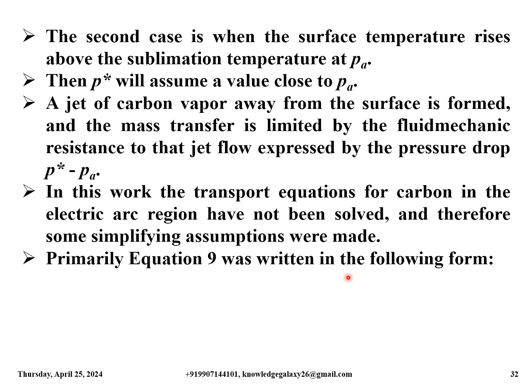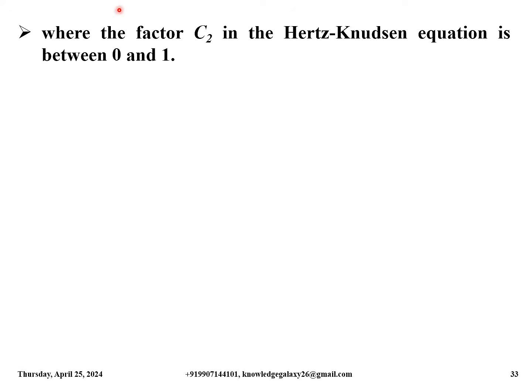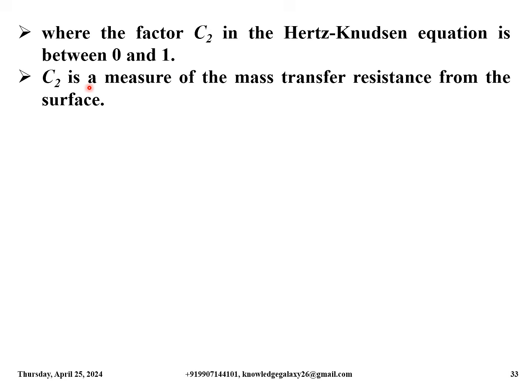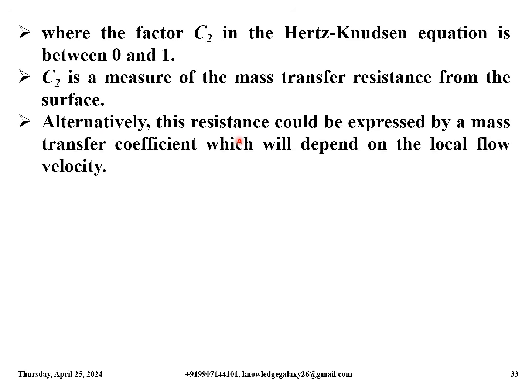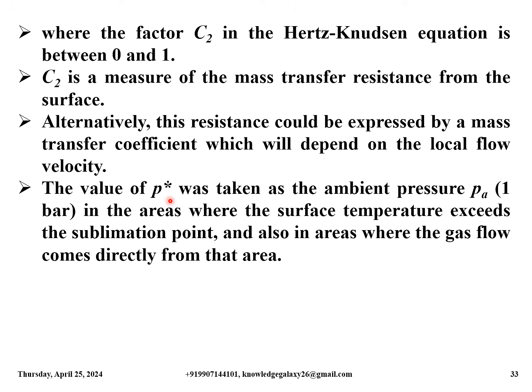Primarily, equation 9 was written in the following form. So this is the modified equation number 9, where the factor C2 in the Hertz-Knudsen equation is between 0 and 1. C2 is a measure of the mass transfer resistance from the surface. Alternatively, this resistance could be expressed by a mass transfer coefficient which will depend on the local flow velocity. The value of P star was taken as the ambient pressure Pa, 1 bar, in the areas where the surface temperature exceeds the sublimation point, and also in areas where the gas flow comes directly from that area.